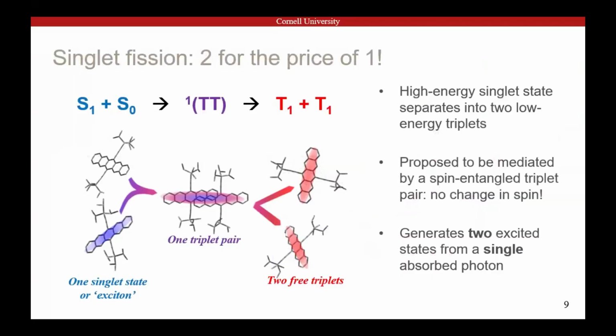You start with a photoexcited singlet state on one molecule. It can share its energy with another nearby ground state molecule. And somehow, through some quick hand waving, you can end up with 2 lower energy triplet states on separate molecules. So 1 exciton turns into 2. And normally, going from singlets to triplets is bad and slow because it's spin forbidden.